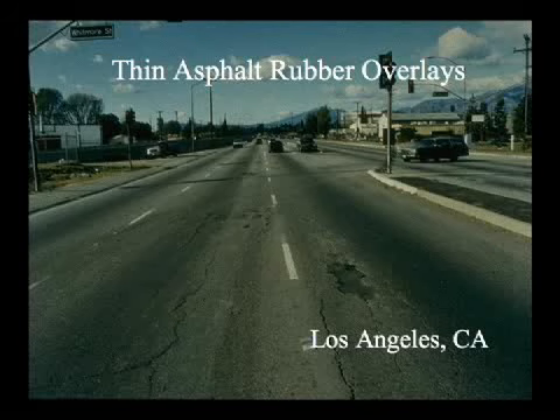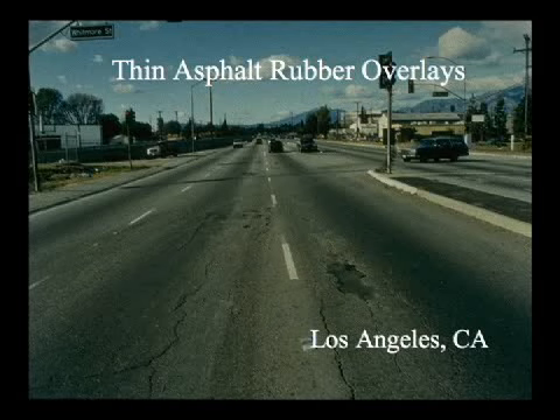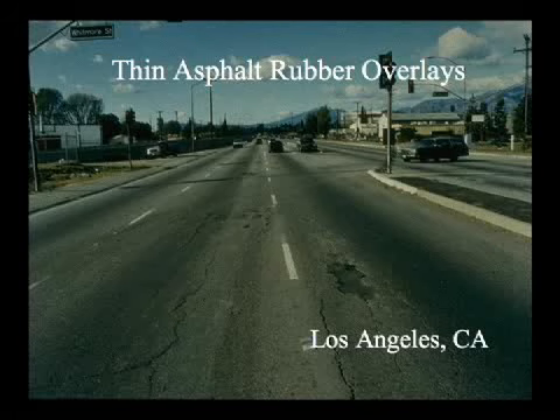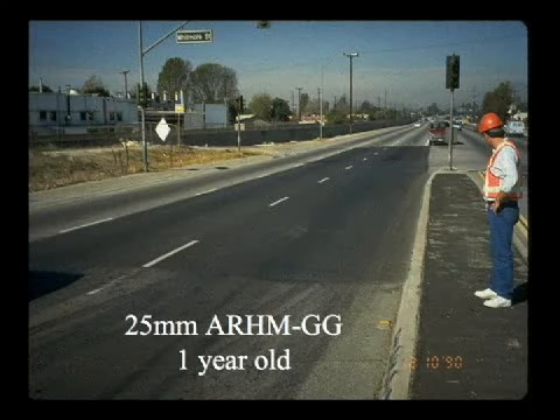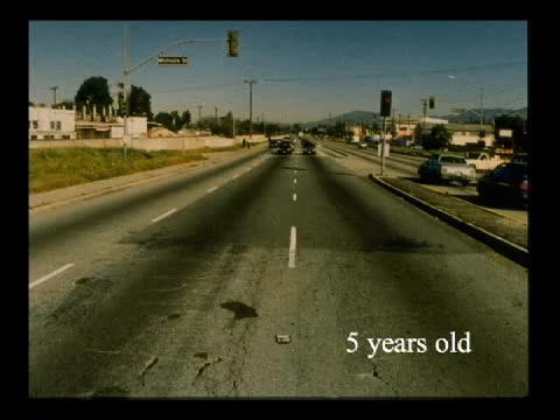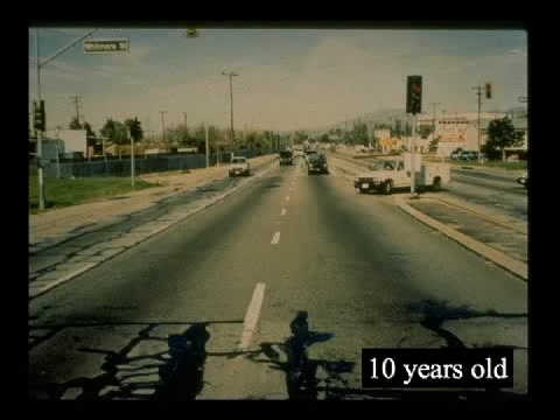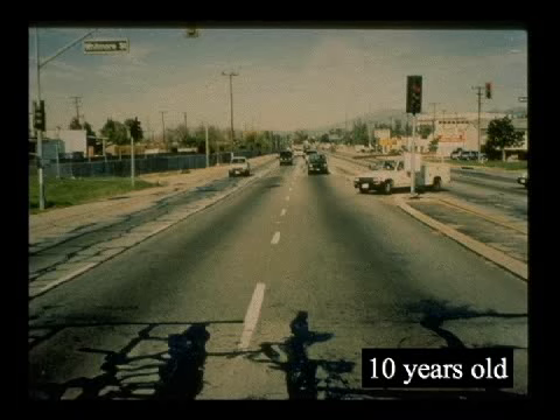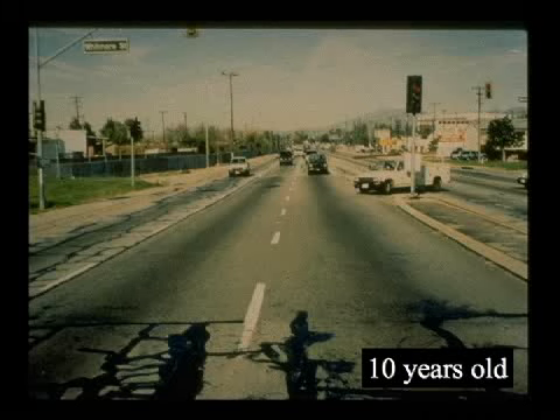and it's still performing today. I'm going to kind of finish with just showing you a picture that really illustrates how well thin layers of asphalt rubber can perform. This was a section in Los Angeles. You can see the potholes here and the cracking, a lot of distress here. This is at 1 year old after we put a 25 millimeter overlay. 5 years old. Now look at the pavement around here. 10 years. There's not a single crack in the 1 inch overlay, but look at the pavement around it. It was such distress they had to come in and rehab it, and they overlaid the section after 12 years. But that really illustrates how well asphalt rubber works in thin layers, on those just few pictures I just showed you.